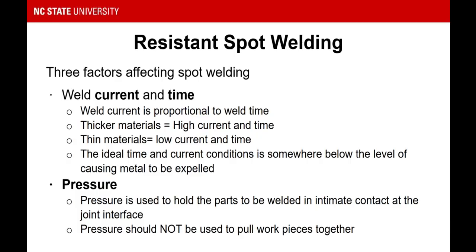If you have too much current or too much time, you will see the metal being expelled or blown out of the weld joint in the form of sparks. In that case, you will likely want to reduce the current and reduce the time. Some folks may reduce one or the other. I typically reduce the current, leave the time the same when I see metal being expelled from the joint. Okay? So keep that in mind when you're welding. If you see a bunch of sparks coming out, you probably need to turn down the current of the machine. Okay?